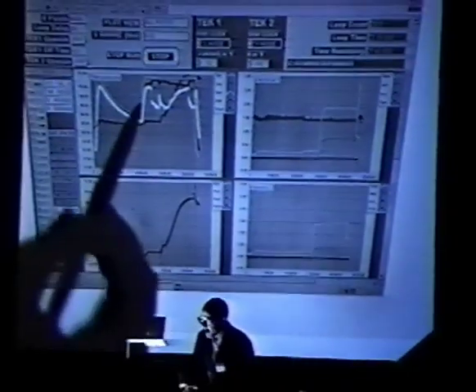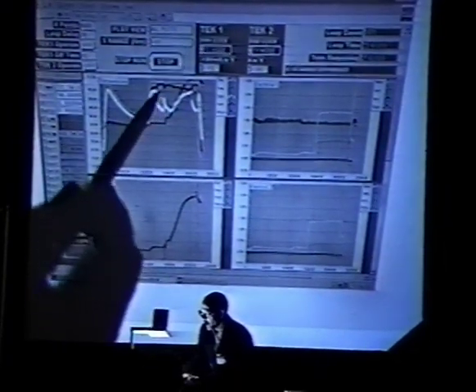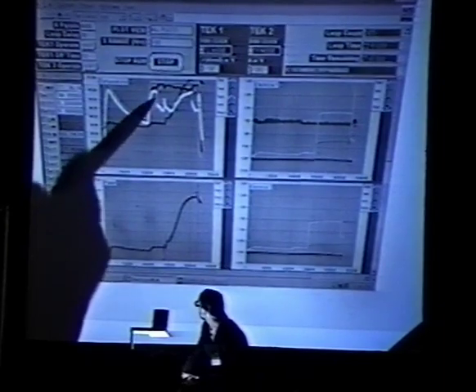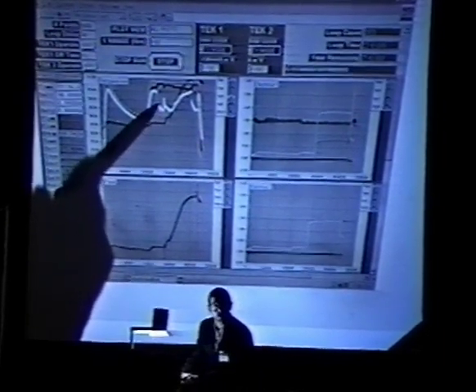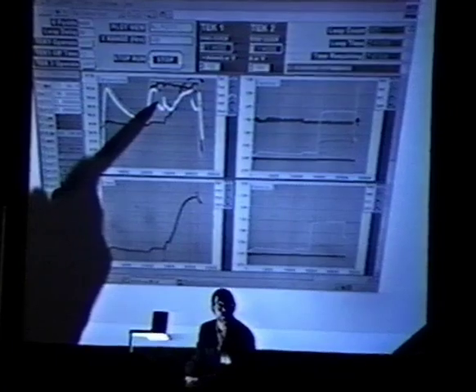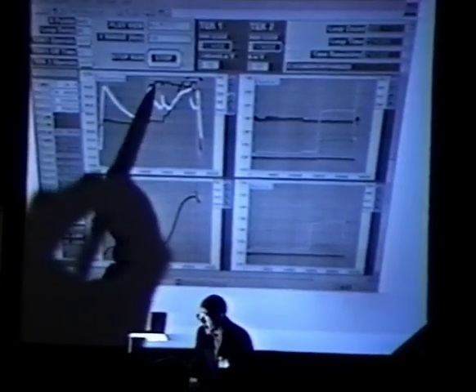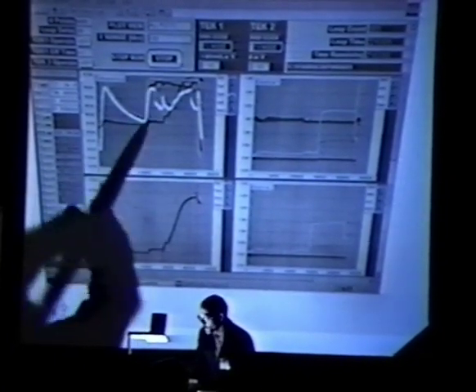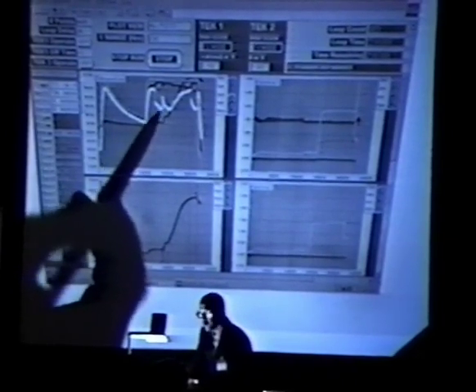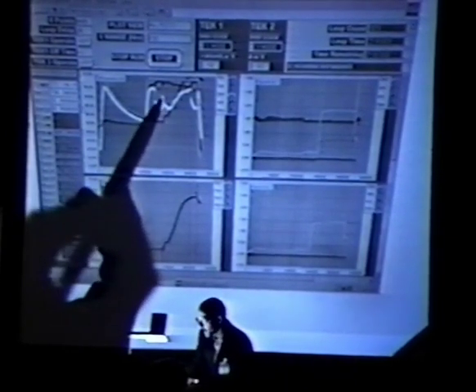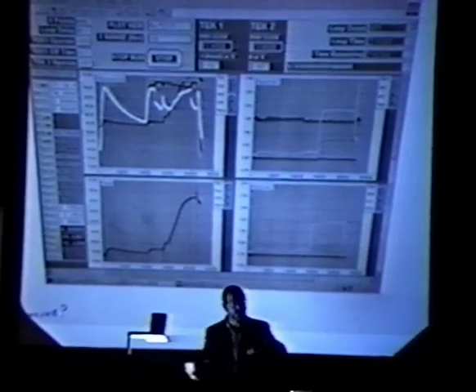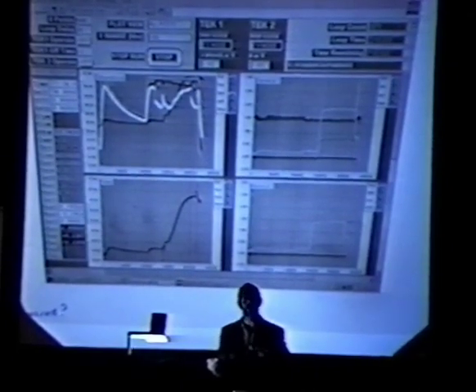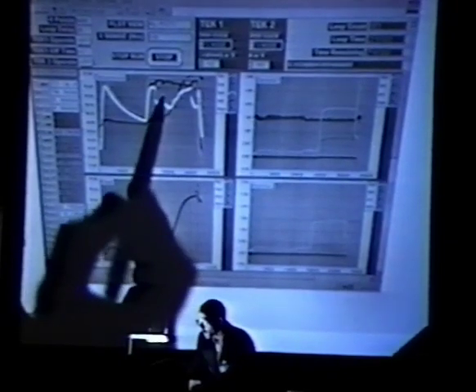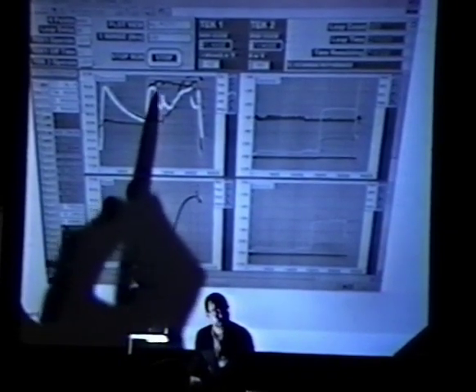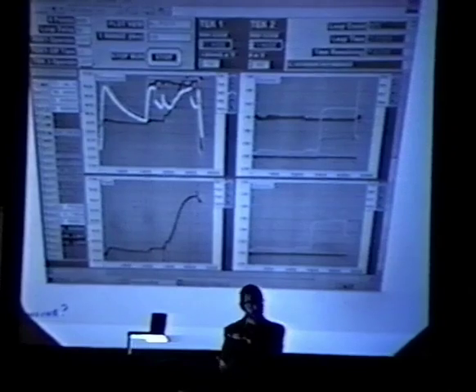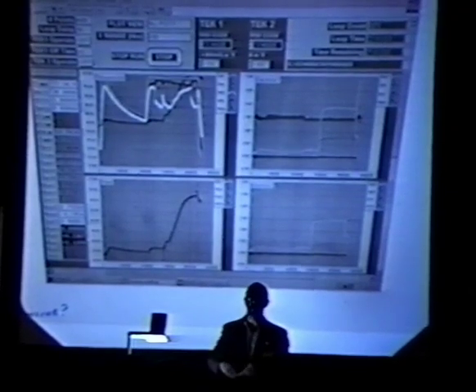What I expected to happen with these temperatures is that when I added that water, the temperature would drop at the top. I also expected the temperature at the bottom to drop, and it didn't. The bottom cell temperature actually went up, and this one came down and continued to go down. The next step, you see this change right here, I stirred the solution with a stirring stick, just manually stirred it very vigorously, and you see these temperatures start to approach each other. And as soon as the stirring was done, the temperatures separated again, related somehow to this water amount.